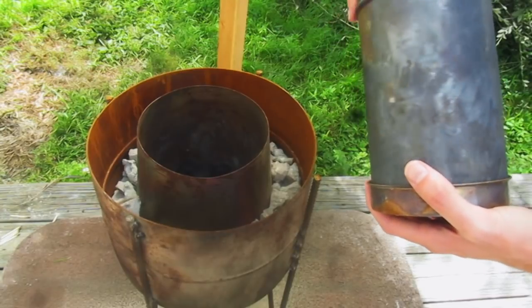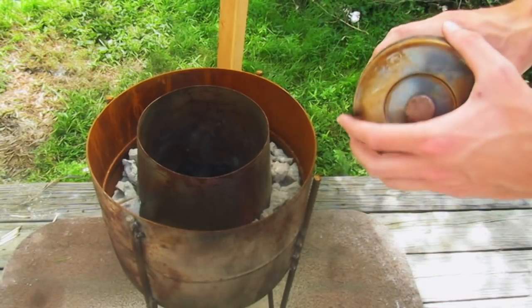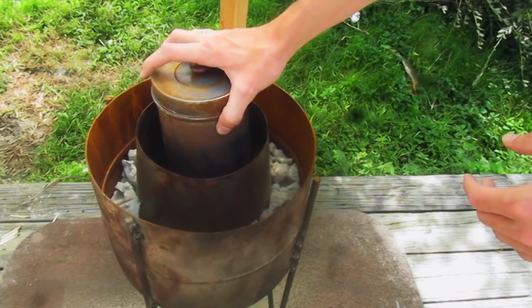This is my stainless steel crucible. I've had a couple of these in the past, but the problem is the molten aluminum actually acts like a solvent and leaches away metal. This will probably only work for about 2 or 3 melts before I have to get a new one.